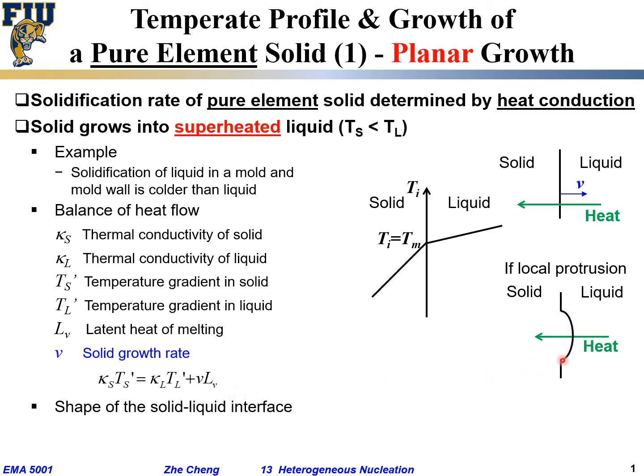We said right at the interface, the temperature would always be the equilibrium melting temperature, T_M, which means along this interface, the temperature remains the same. Then, with a protrusion like this towards the right, the interface still grows towards the right, because the material is going through solidification, the solid is expanding, and the interface moves towards the right. Under such a situation, deep within the solid, the temperature does not change. Deep within the liquid, the temperature does not change. Right at the interface, the temperature is maintained at the melting temperature. Then, this is our assumption: no temperature change in deep liquid, in deep solid, and at the interface.